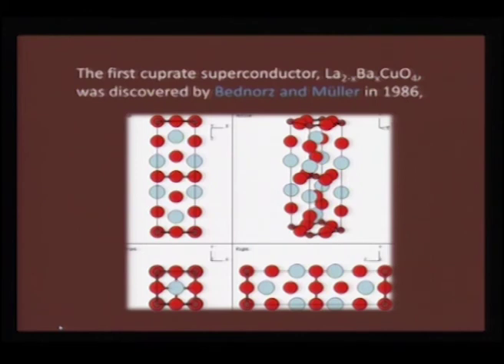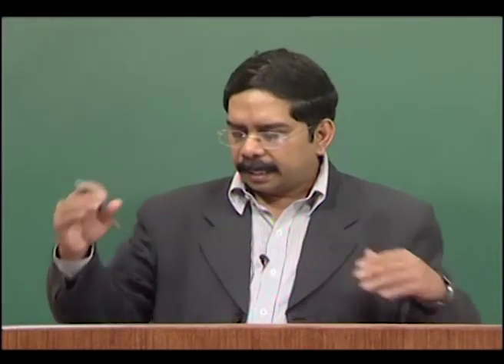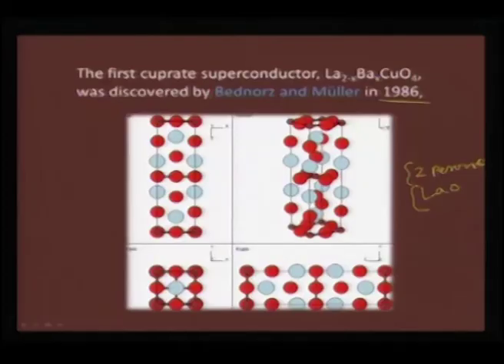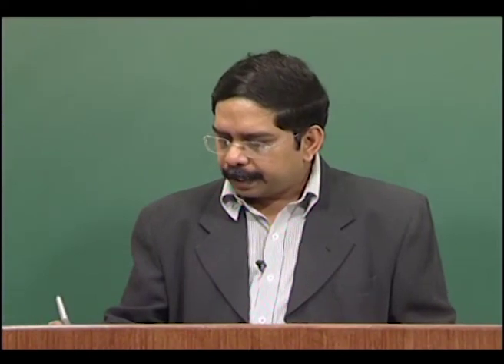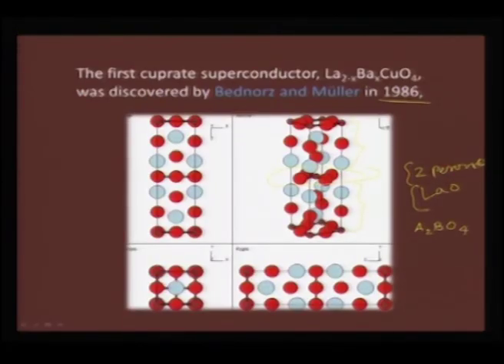So, the first cuprate superconductor, La2-xBaxCuO4, was discovered by Bednorz and Müller in 1986, and if you view the crystal lattice from different perspectives, this is what you would see. And as you see here, this is nothing but a perovskite. Two perovskite layers are sandwiching a LaO layer. So, you have two perovskite layers, and in between these two perovskite unit cells you have a lanthanum oxide sheet which is separating them, and that is what you would see here. Roughly this is one perovskite and this is one perovskite, and the intermediate layer is your lanthanum oxide. So, that is exactly what brings in the layered nature. A2BO4 is nothing but ABO3 repeated with an interlayer AO.